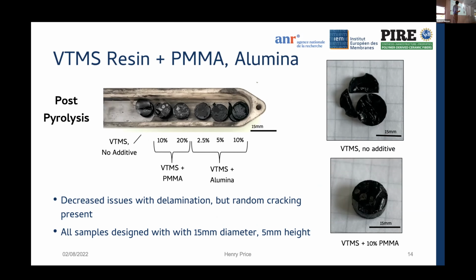So now a bit on the microstructure. Again, this goes back to this increased amount of cross-linking, which I think may have contributed to this more uniform, more smooth sample surface that you see. So this is an unpyrolyzed sample and a pyrolyzed sample. And just a quick comparison to the microstructures of the other resin chemistry based samples, again, unpyrolyzed and pyrolyzed.